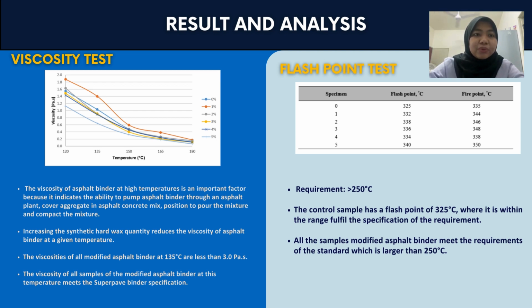This test is to determine whether a sample mixture of vapor and air is flammable. The requirement is more than 250 degrees Celsius. The control sample has a flash point of 325 degrees Celsius, which is within the range, and all the modified asphalt binder samples meet the requirements of the standard.